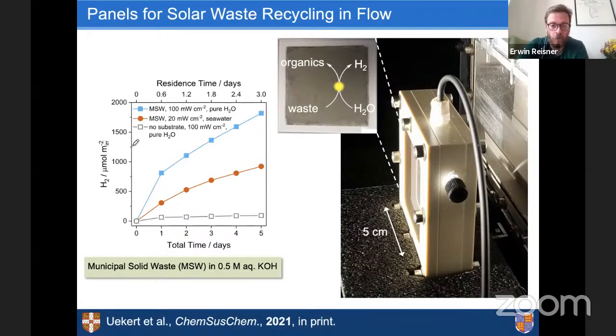And this works, again, here showing the hydrogen yield versus time, a couple of days, we have quite good activity. And it's also, as I mentioned before, not very sensitive. So even if we do the chemistry not in pure water, we can use seawater, we can use contaminated plastic. It's quite a robust system. And in fact, what we've been using here is real municipal solid waste. So it's actually not a purified waste, it's a true waste stream.